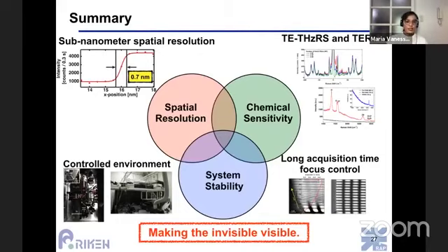But for more robust samples, so for example, graphene or maybe silicon, as long as the temperature does not cause a Raman shift due to heating, that is still okay. Because for Raman spectroscopy, we usually observe the Raman shift. And this shift can be caused by strain, by interaction with another molecule, etc. But we want to make sure that shift is simply due to the interaction or due to the strain experienced by the sample, and not due to the heating, which can also cause shifting.